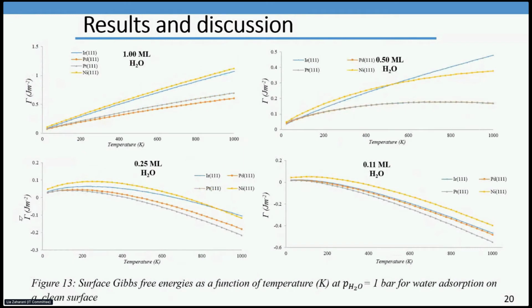This figure shows the Gibbs free energy as a function of temperature for water adsorption on the clean metal surface. The palladium 111 surface was the most stable for the metal and water adsorption at all the adsorbed coverages, followed by the platinum surface, followed by the iridium surface, followed by the nickel surface.